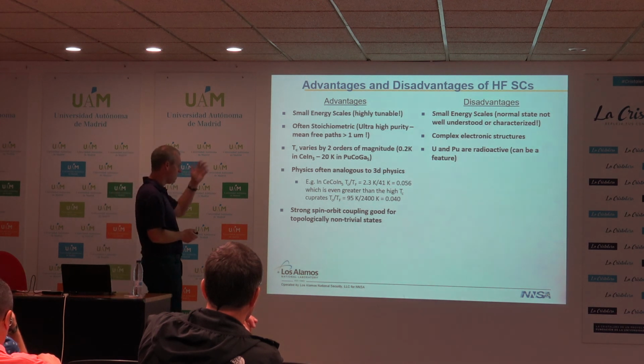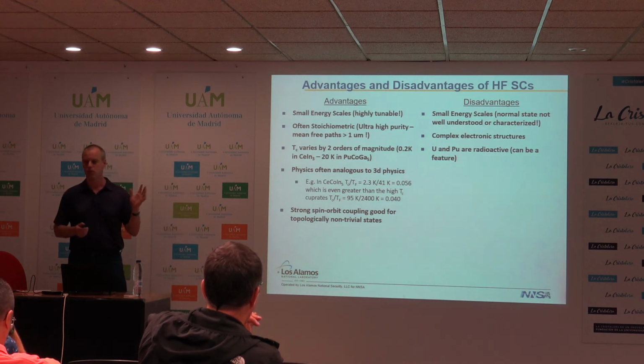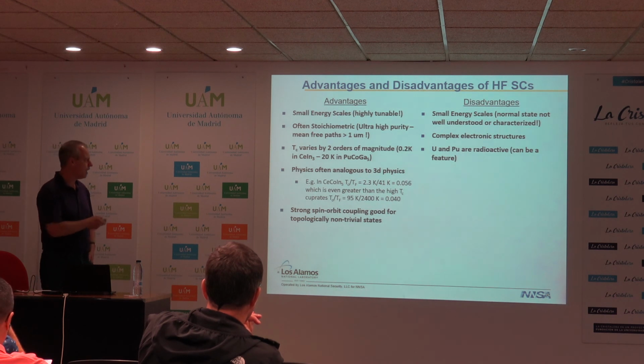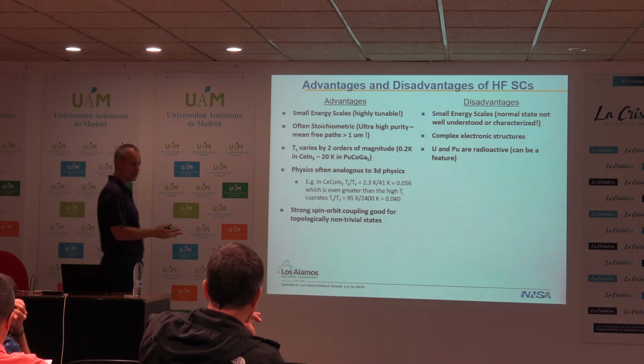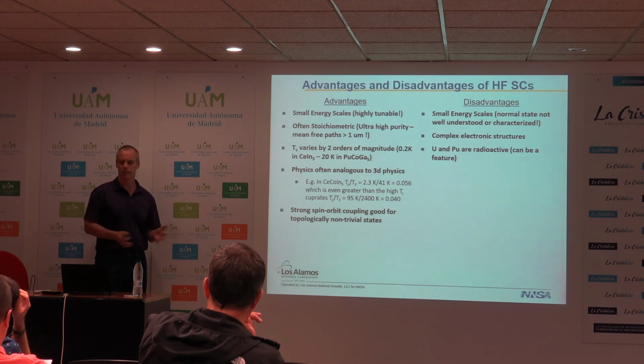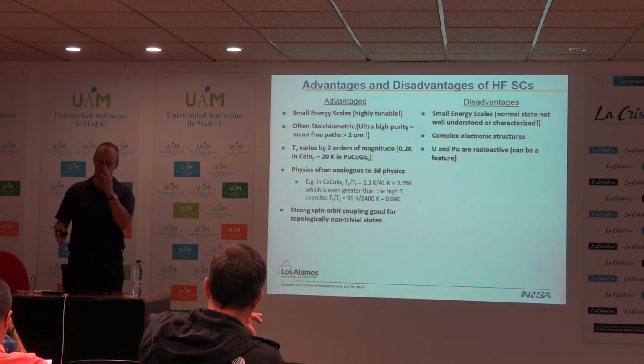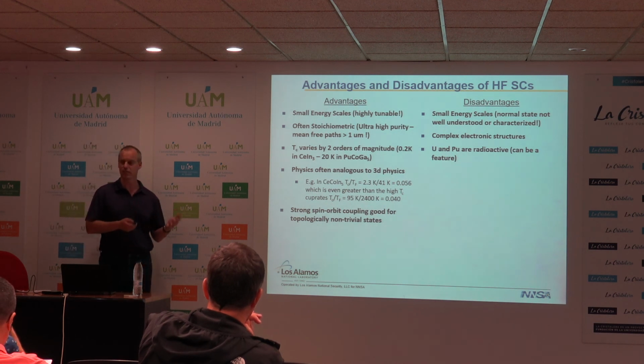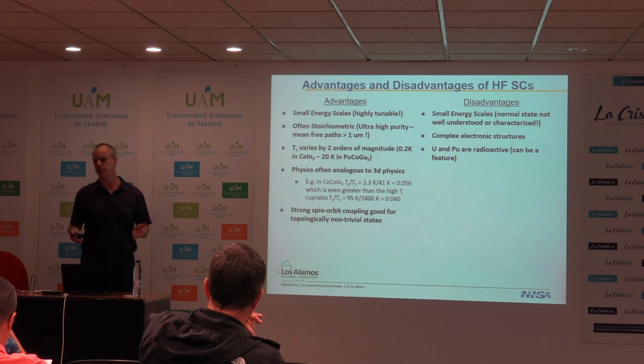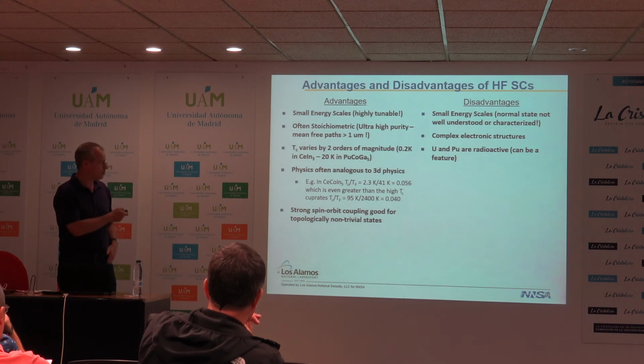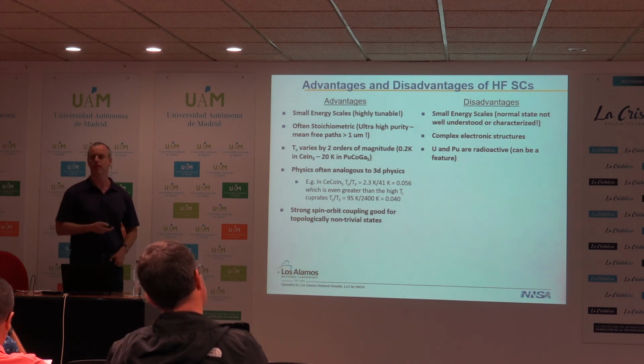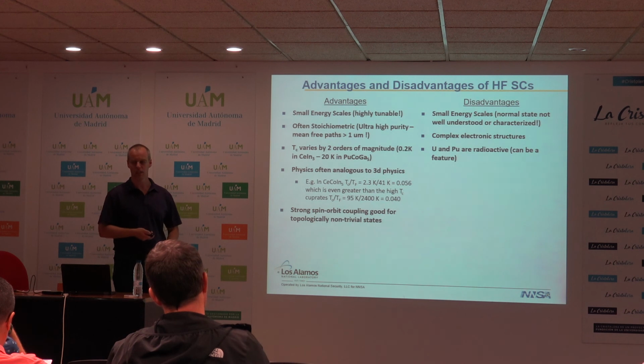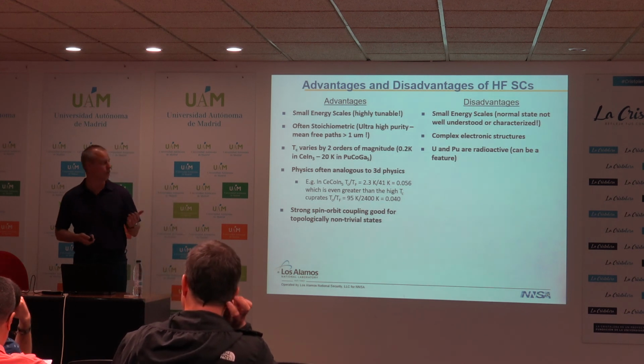Okay, so I'll end to summarize. I'm trying to advocate for studying heavy fermion superconductors, and I think one of the strongest advantages is in fact the small energy scales. It makes the systems highly tunable with clean tuning parameters. So you can use pressure and change the ground state of the system and explore it. Now, the small energy scales obviously are difficult for some experiments, and doing measurements under pressure is just not feasible at all. I mean, you can't do an ARPES measurement under pressure. And this turns out to be a disadvantage for the system as well, right? The small energy scales do mean that it is difficult in particular to characterize the normal state.